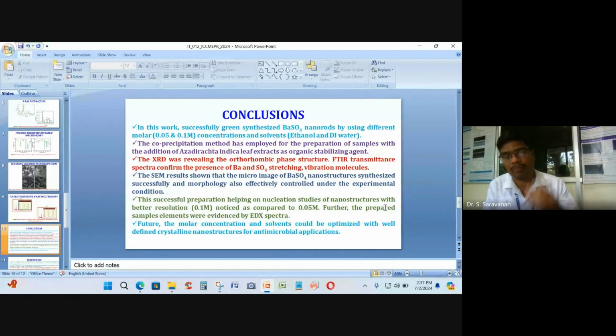Again, figure B, you can see that this is the deionized water-based nanostructures. You can see that here also barium, sulfur, and oxygen are present with impurities. However, the weight percentages are lower compared to ethanol. You can see barium 32.92, sulfur 9.84, and oxygen 28.86. So these are the percentages. However, the best structures we got were from DI water-based barium sulfate.